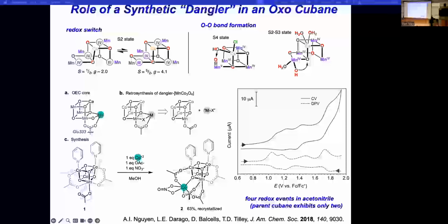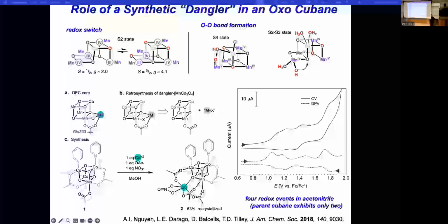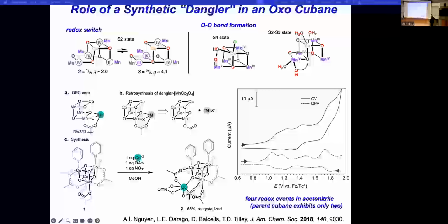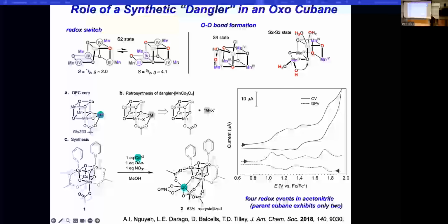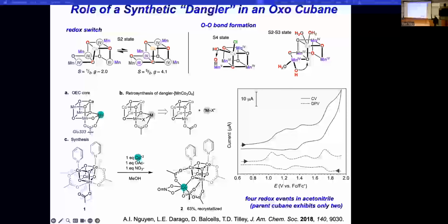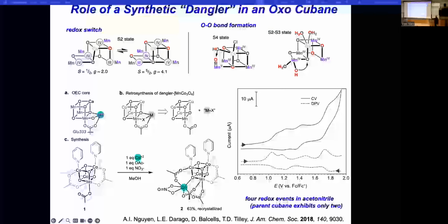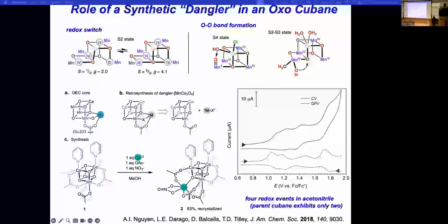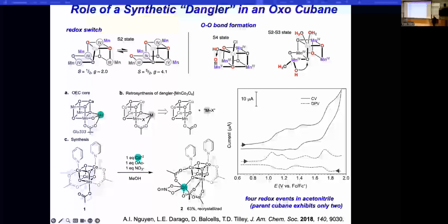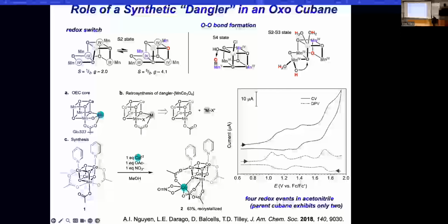We were able to make one, which is the species that you see down here at the bottom. And this is by adding cobalt 2 to the manganese complex that I showed earlier. And that gives this dangler species, which has interesting electrochemistry in that the redox events are separated energetically, unlike they are in the parent cube. We can't really assign each of those events yet, but it's an indication that that dangler can really dramatically affect transformations of the cluster as a whole.